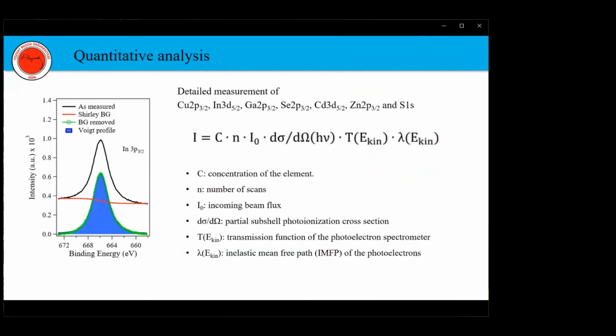In order to get quantitative information, we recorded the detailed core level spectra of all the constituent elements. We then integrated them over a Shirley background using Voigt profile, which is a convolution of a Gaussian and a Lorentzian profile. The signal intensity of an individual peak is then calculated as the area of the Voigt profile, the blue area here. The intensity of an individual peak is then related to many factors. Therefore, it has to be normalized to these factors before any comparison between two different peaks.